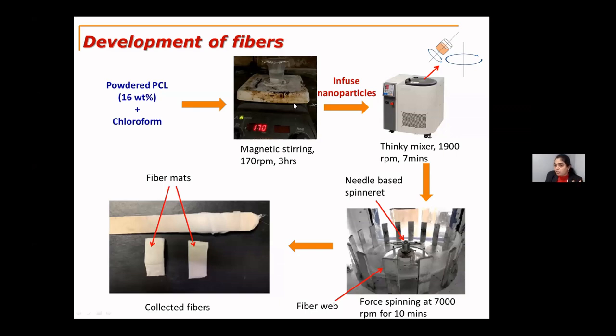When we infuse the nanoparticles, they will not be easily dissolved using magnetic stirring. So these nanoparticles have to be mixed separately. And for that, we use a Thinky mixer. This is a planetary mixer which mixes under vacuum. It goes up to 2000 RPM. I chose 1900 RPM, and I used it for 7 minutes to mix these nanoparticles. If we choose a longer time, the nanoparticles get agglomerated because hydroxyapatite particles easily agglomerate. So that is the reason we chose 7 minutes for planetary mixing.